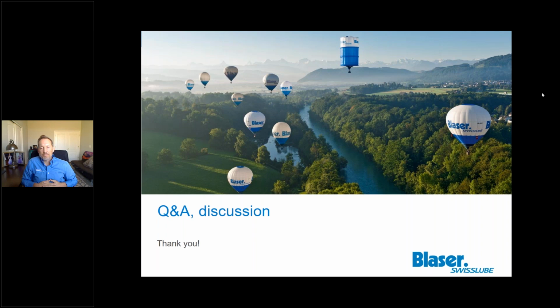And Randy, just to add to that, with a synthetic fluid, I think it's much better to use an RO or DI water system, because you don't get the buildup of salts or hardness materials that can cause white scaling and things, and maybe even some stability problems with the fluid. Would you agree? Yeah, hard water can cause a problem for all different types of cutting fluids, whether it's a full synthetic or not. Full synthetics are more prone to sticky residues when water hardness accumulates too high. A lot of synthetic fluids also may have rusting issues quicker than a non-synthetic if the chlorides are too high. So it's very important that your chloride levels remain low by using RO or DI water.